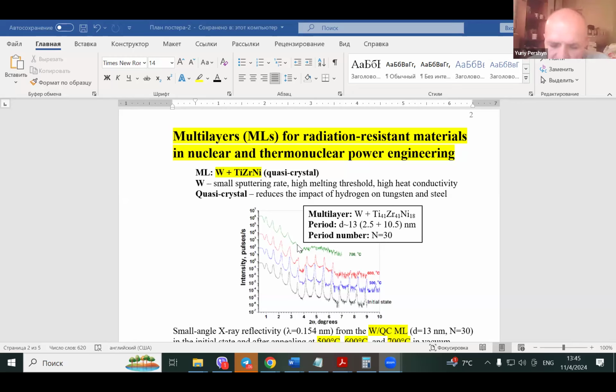Tungsten is used as plasma facing material due to small sputtering rate, high melting threshold, and high heat conductivity. However, due to the gradual accumulation of light isotopes, for example, deuterium, tritium, internal macro stresses develop in this material, leading to the formation of surface cracks. Titanium, zirconium, nickel quasicrystal can function as reversible hydrogen absorber in solid solution form without hydride formation and subsequent hydrogen release. In such layered system, quasicrystal reduce the effect of hydrogen on tungsten.